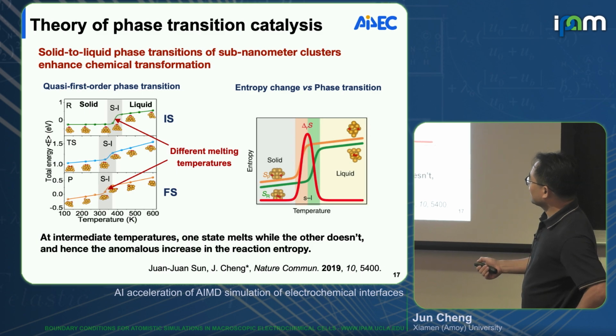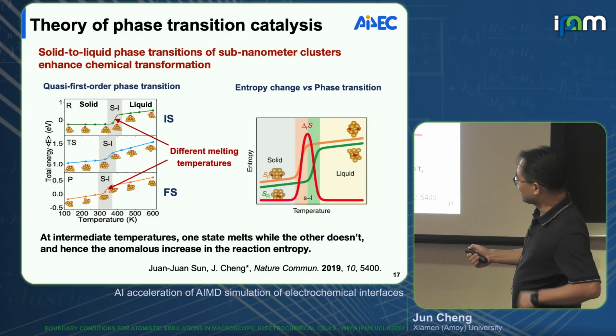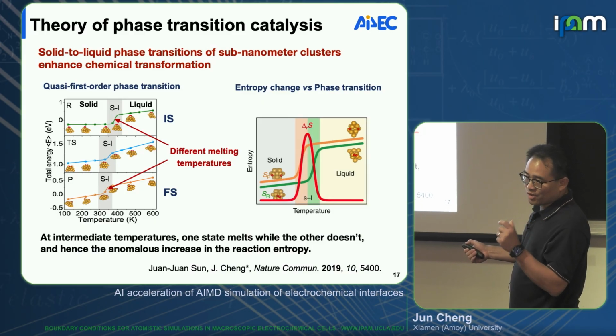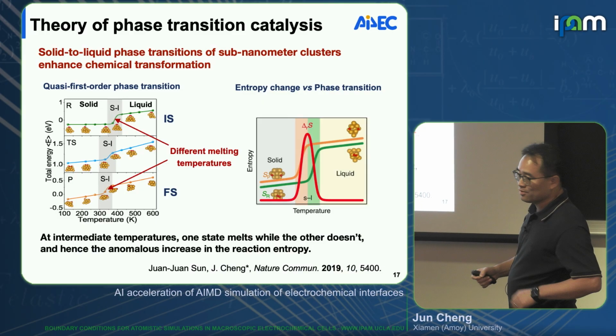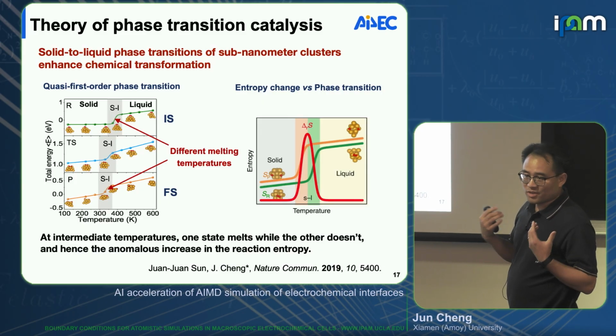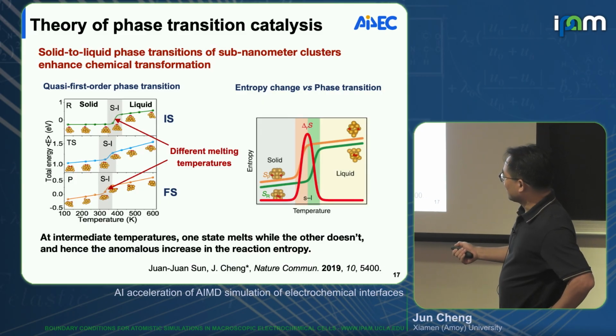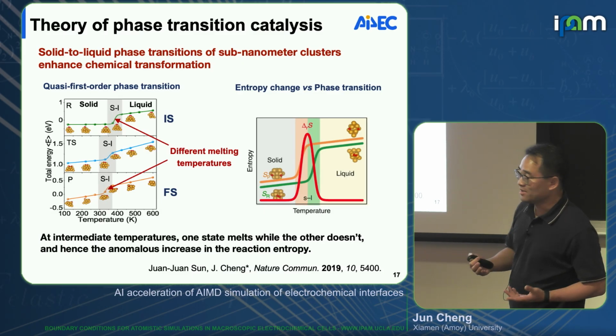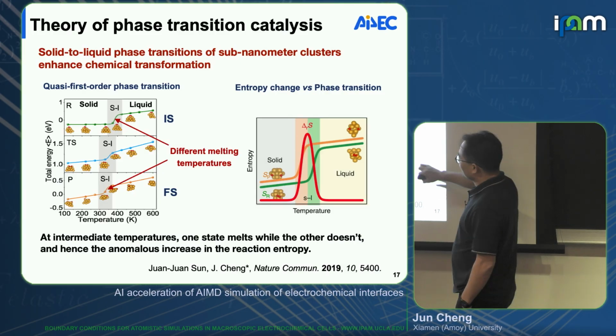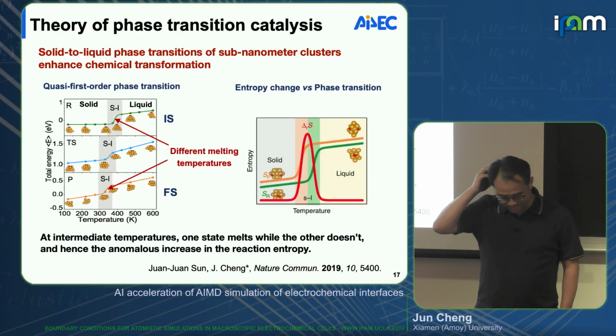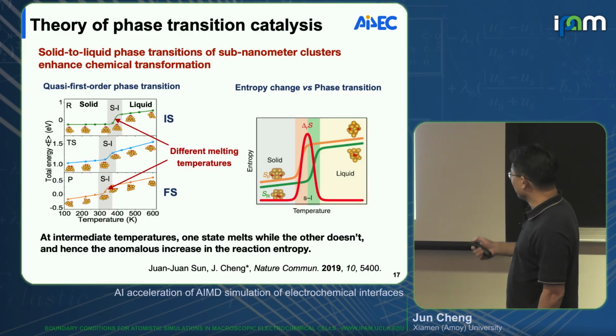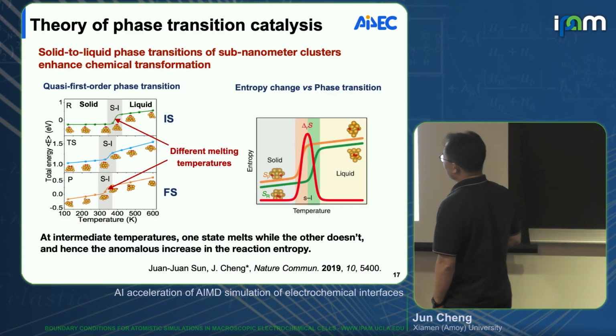And interestingly, for different states, reactant and product: the reactant will be one oxygen molecule adsorbed on the gold cluster. The product will be the dissociated product, two oxygen atoms adsorbed on the gold cluster. The transition temperatures are actually different. Using this, I will quickly explain why we have this huge peak in the reaction entropy.